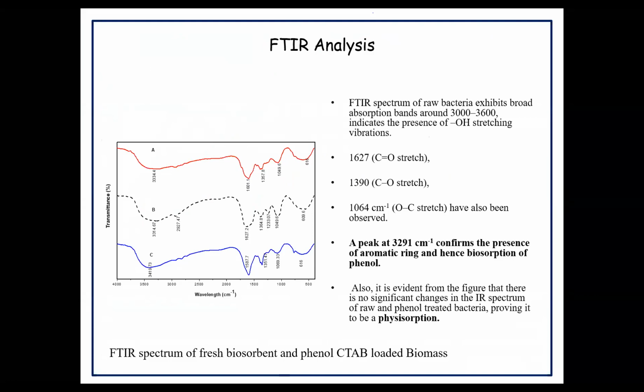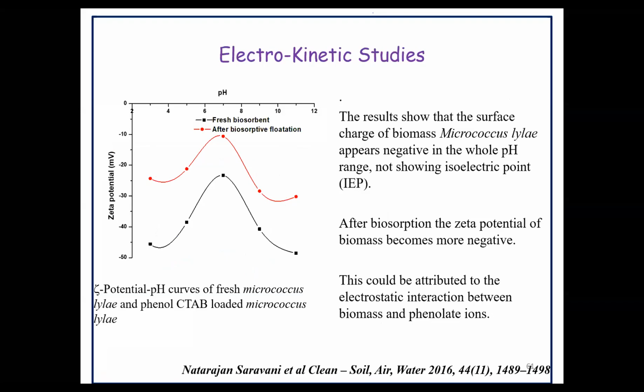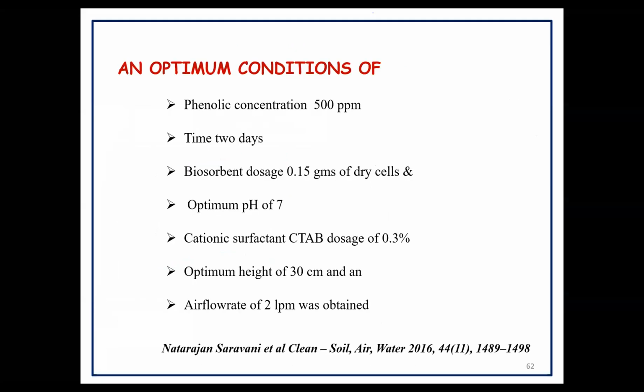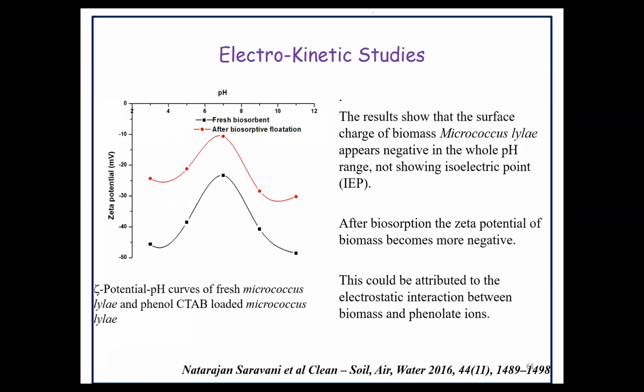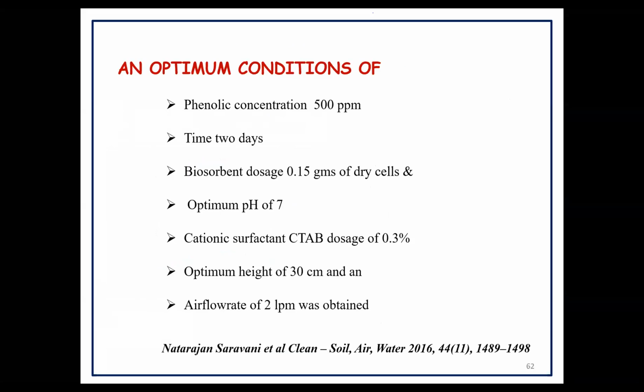For the analytical part, we have used FTIR studies to confirm whether phenolic compounds or metal ions have been removed, have been adsorbed onto the foam. We got the results that the phenolic compounds have been very nicely adsorbed onto the foam surface. We have also done CTAB zeta potential studies to find out the electrostatic interaction between the foam and the phenolic compounds. And these are the results we got for the optimum conditions.